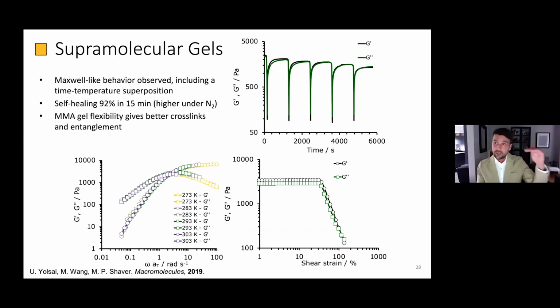And so we have a slow reduction in terms of the number of crosslinks we get over time. From these other systems, we can see that we have a Maxwell-like behavior observed. The time temperature superposition suggests these are acting as supramolecular gels. And I can change the flexibility of a system by changing my co-monomer. So I get a very different performance based on MMA than I do for having styrene as a co-monomer.